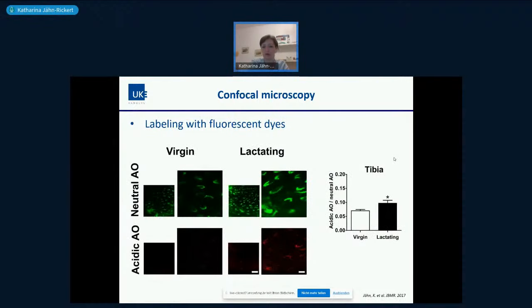You can also not just use transgenic mice, but you could try labeling and then image your fluorescent dyes within the bone matrix. So here we also looked for the acidification again in the same experiment, and we injected the mice with acridine orange, which in a neutral pH fluoresces green. Here you can see it infiltrated the osteocyte lacuna, both in the virgin and the lactating mice. Only if there's an acidic environment, this should turn red. And when we quantified this, with the lactating mice there was much more of this acidic form in the graph compared to the virgin situation, suggesting that there was an acidification happening in the osteocyte lacuna.